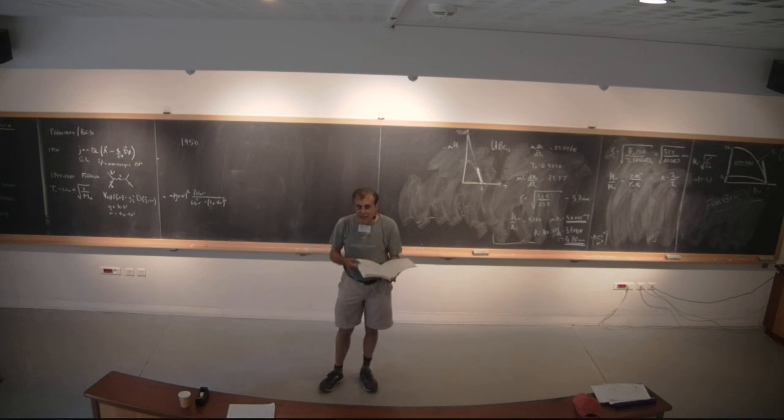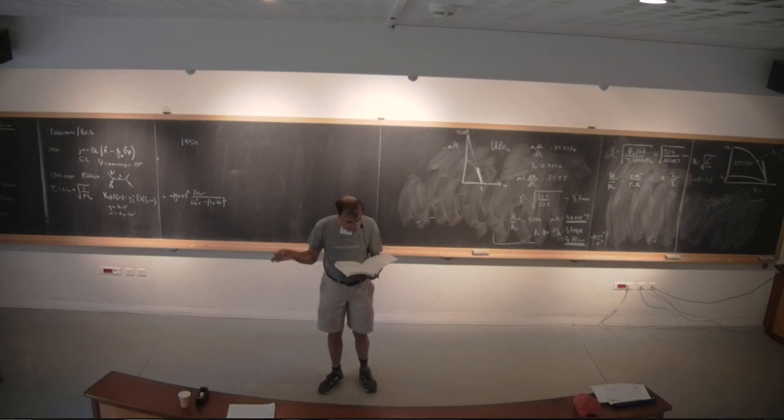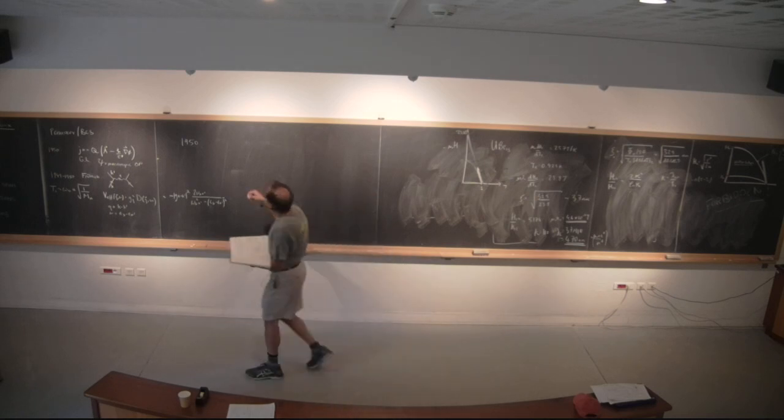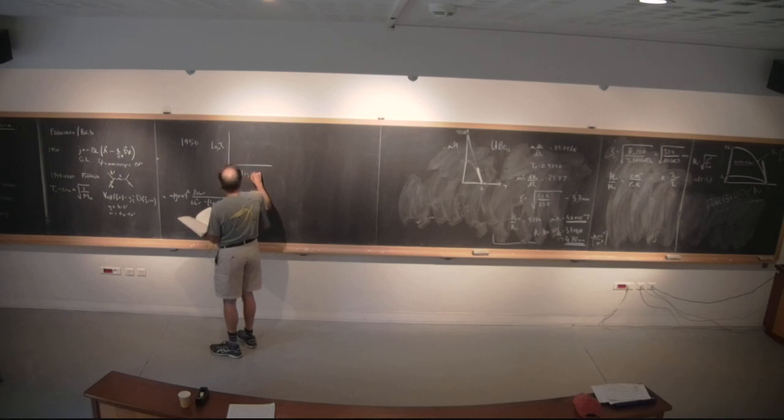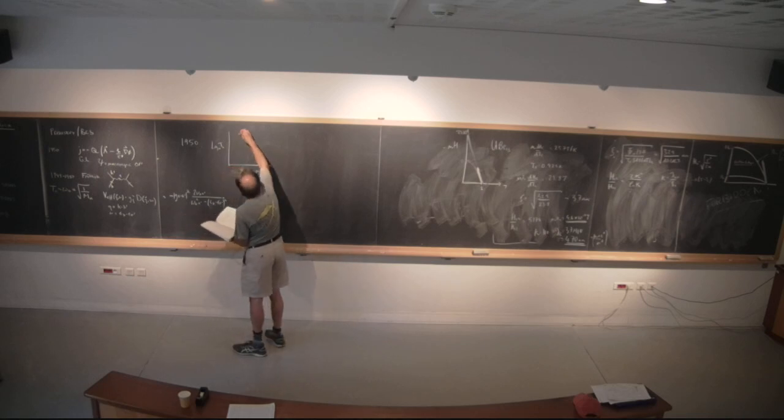Okay? And since the isotopes of mercury have different nuclear masses, you can get enough of a range to actually measure log to the base 10 of Tc versus log to the base 10 of m. And the curves that came out of that basically had a very nice fit to -1/2.